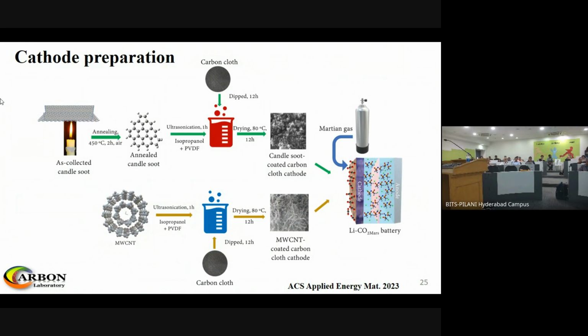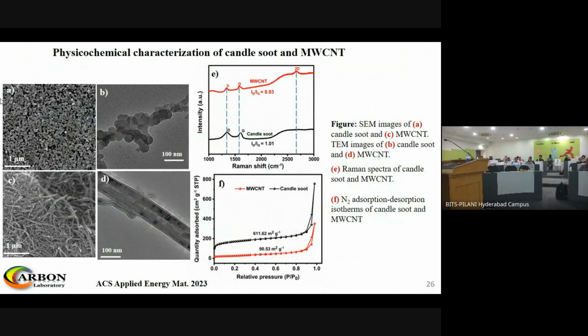Similarly, for comparison, we have used the multi-walled CNTs. Again, we prepared the solution of multi-walled CNTs, put it on the carbon cloth, and used it as an electrode, cathode. And then again, we have used it for the Martian gas system. So this is typically how this looks. This is candle soot, this is multi-walled CNT. We can see the surface area of multi-walled CNT is around 90, while candle soot is increased to 600 by activation. And again, the candle soot ID by IG ratio was originally 1.12, which is now reduced to 1.03. It's quite an amorphous region, unlike the multi-walled CNTs.